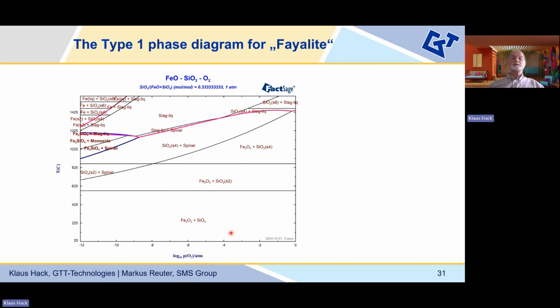And I hope you all remember this is now a type 1 phase diagram, where both axes are potential variables, and the one is the classical temperature, and the other one is the classical oxygen partial pressure. And then we have here somewhere 1250, and you can see, yes, there is a wide range where there is liquid slag. When you go to lower temperatures, yes, then you also find there is fayalite possible, but it is at very low oxygen partial pressures, and it is also at reduced temperatures. Otherwise, fayalite doesn't really play a role here. It's really just a name which people like to apply for these slags.